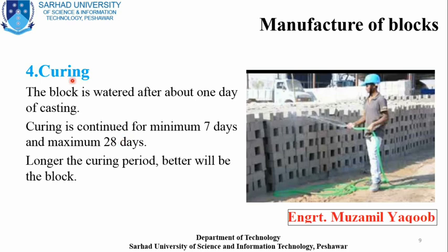And the last stage in the manufacturing of block is known as curing, right? So curing is very important. If we do not properly cure our blocks, it will decrease its strength by 20 to 30%. And according to experiments, curing of 7 days is the minimum required, and maximum 28 days are required to achieve its 100% strength, right? In other words, you can say the longer the curing period, the better the block.